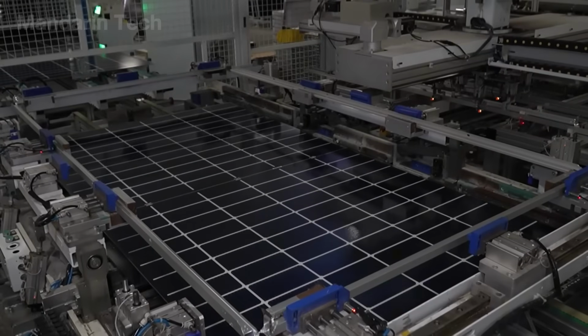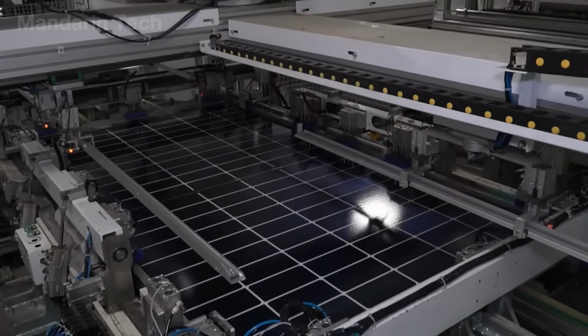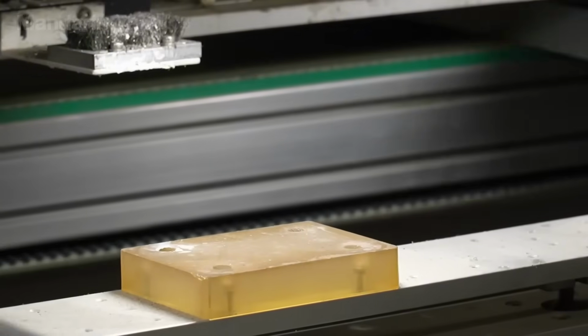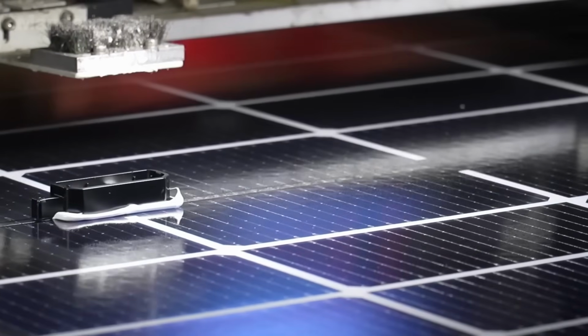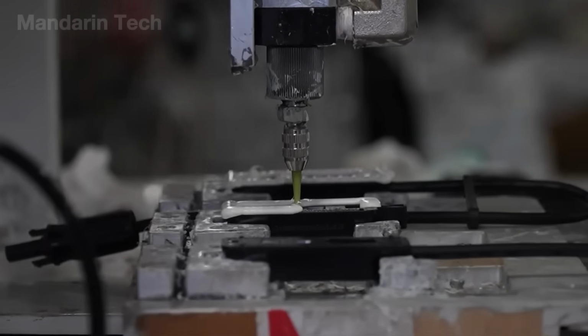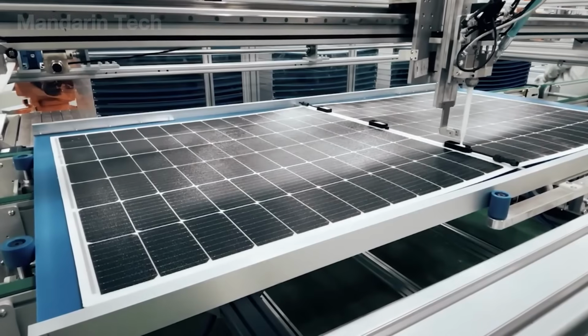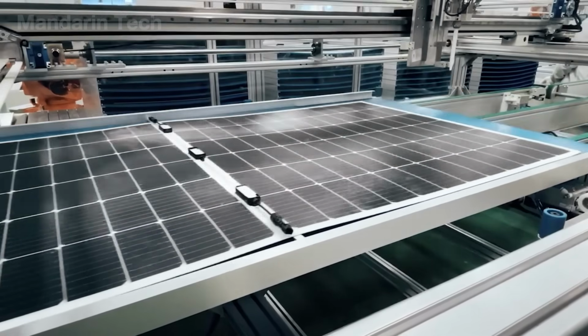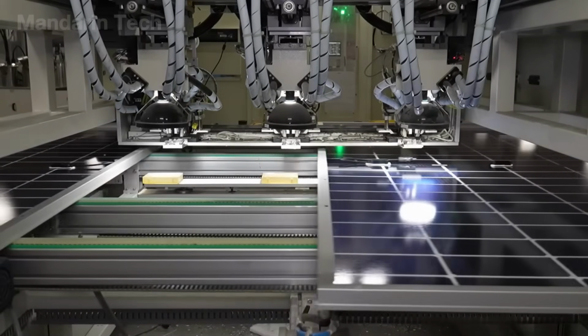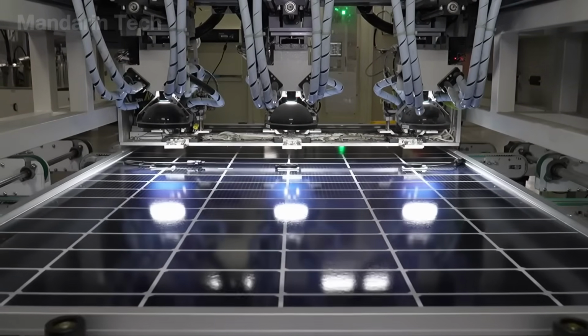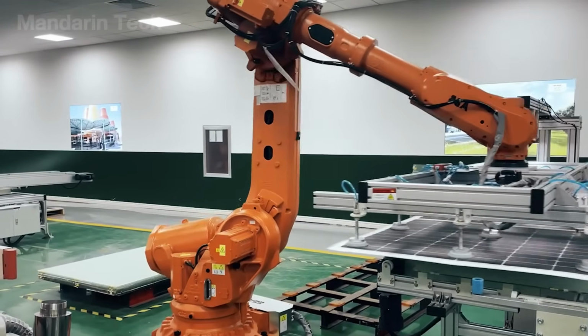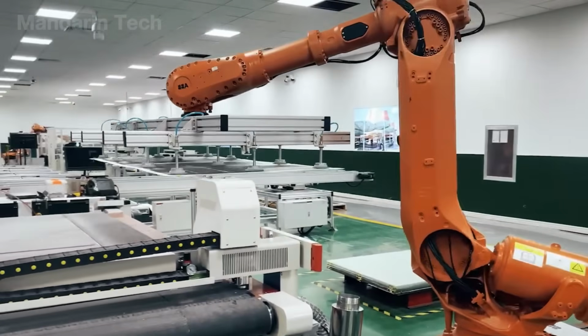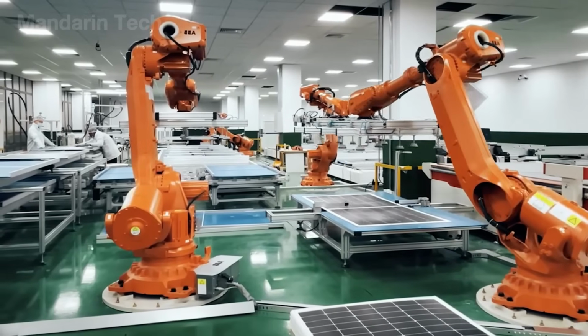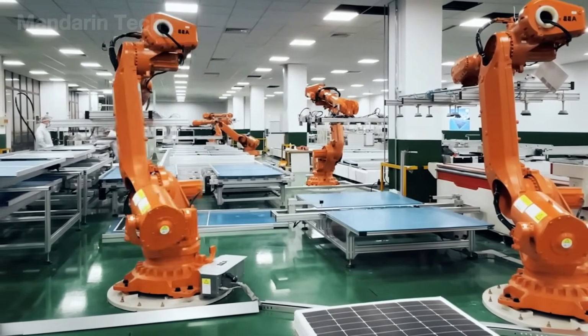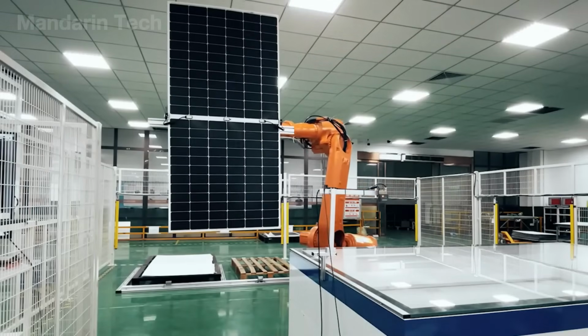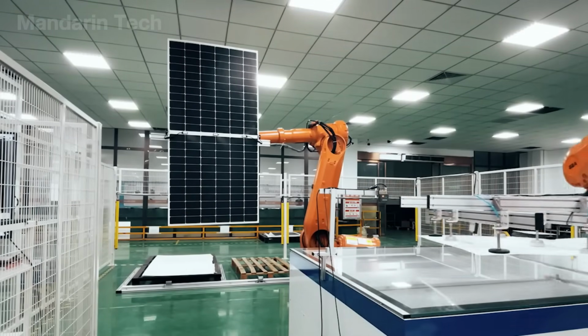Automated robots attach lightweight aluminum frames using heat-resistant silicone, securing the glass edges and improving heat dissipation. These slim frames, only a few millimeters thick, can withstand winds up to 2,400 pascals and snow loads over 5,400 pascals. On the back, a sealed junction box with UV-resistant cables and epoxy coating ensures perfect insulation, with every connection tested at 1,000 volts for safety in extreme conditions.